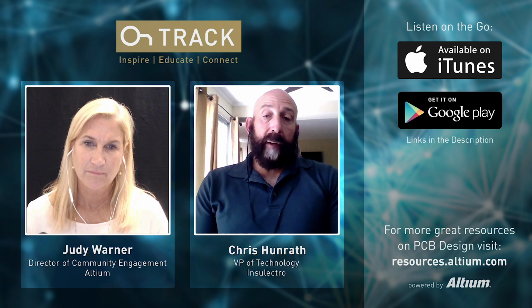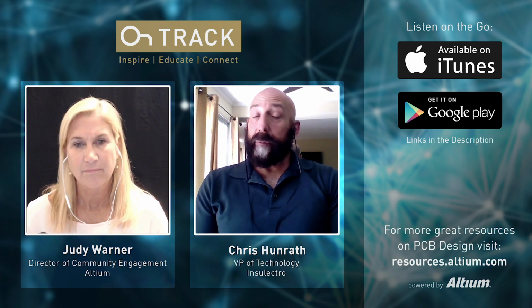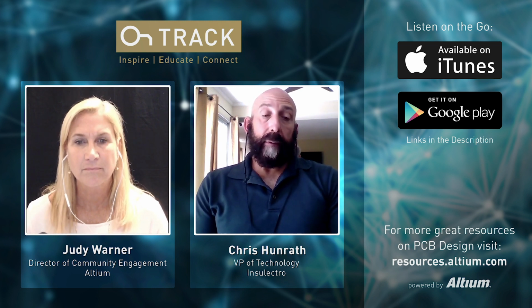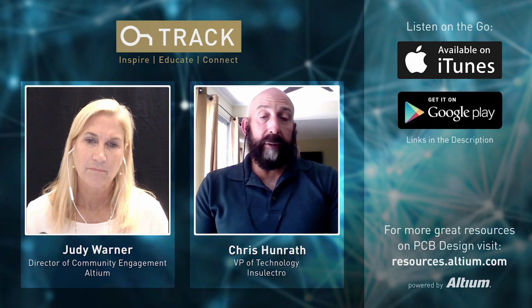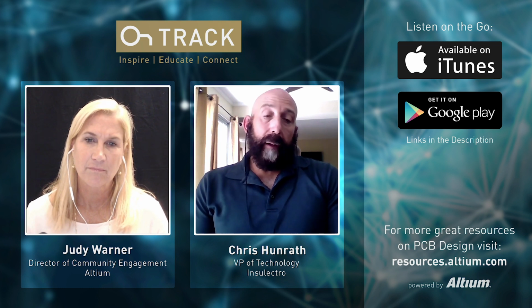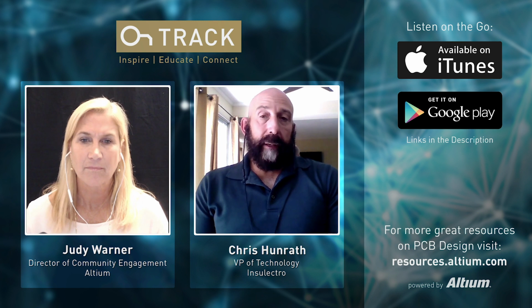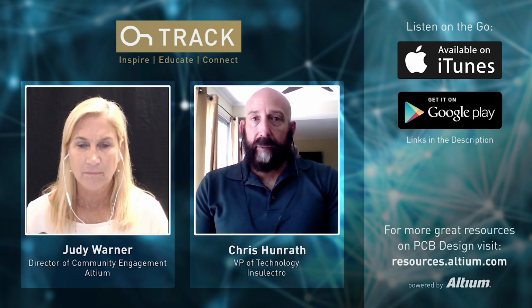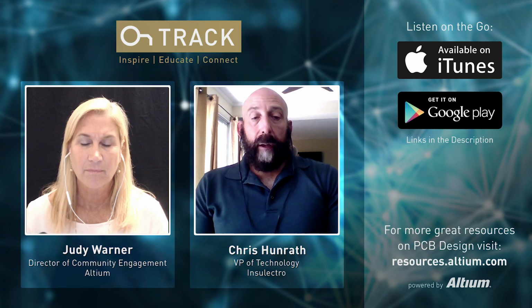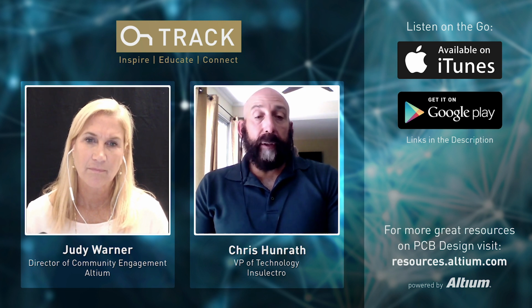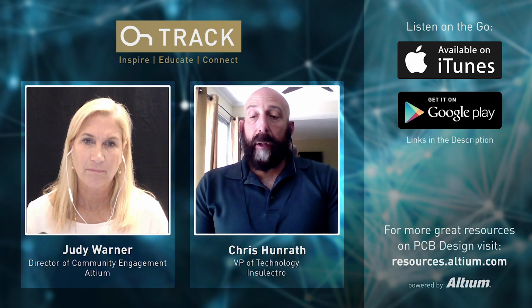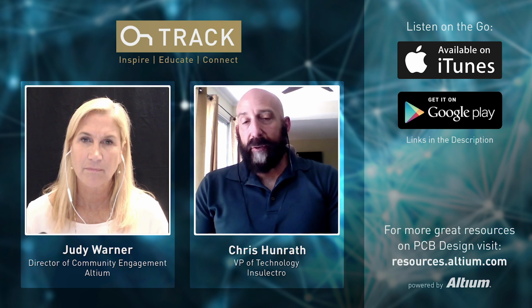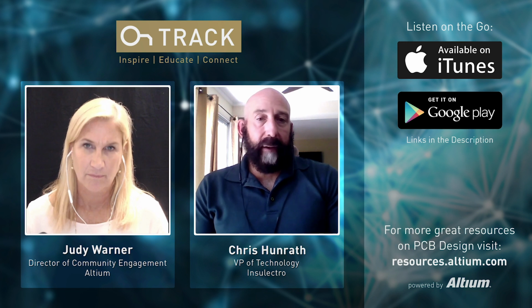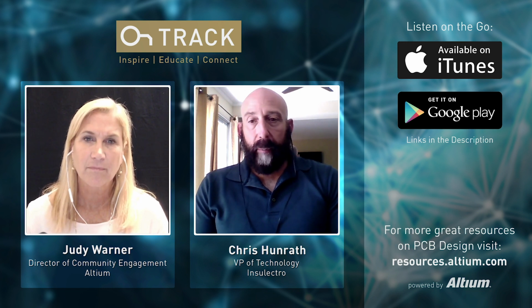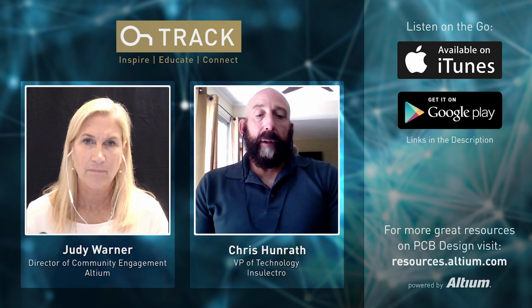In this case, we were talking about a polyimide film that's typically used for flex circuits, which can be used in a rigid board as a thin dielectric layer. Polyimide film is nice because it has very high dielectric withstanding voltage, and you can make it really thin. So you can build it into a rigid board and get the properties you need to get rid of those capacitors. But that also leads into hybrid constructions. Now we're mixing materials. You might have FR4 and polyimide film. How do you process them?